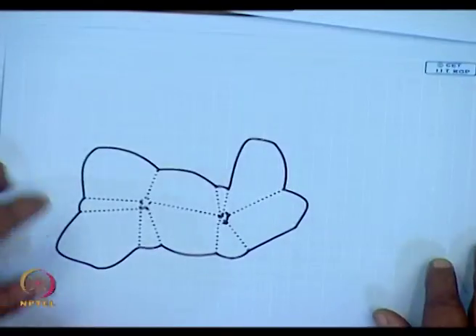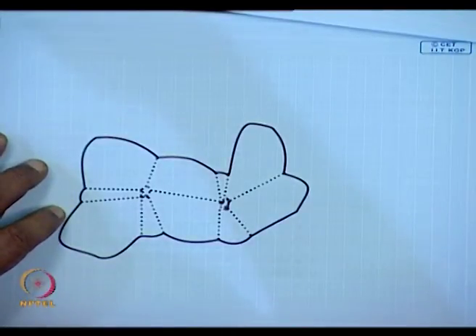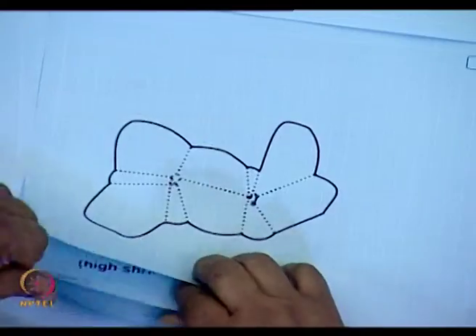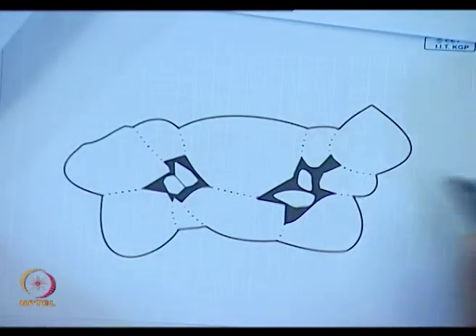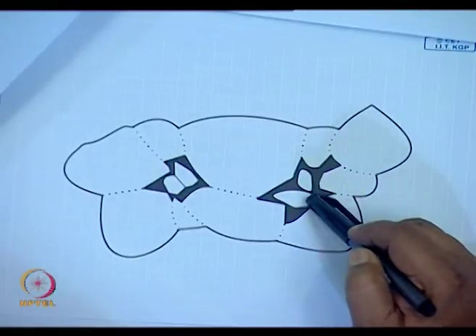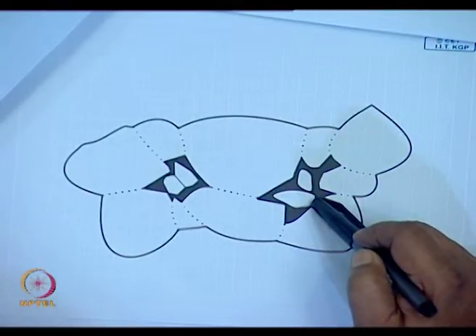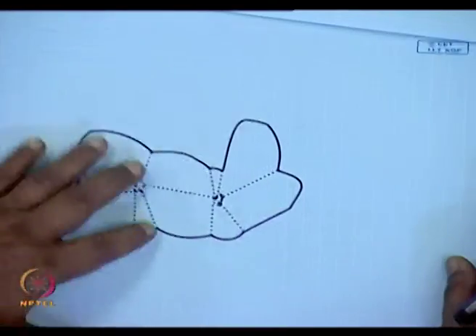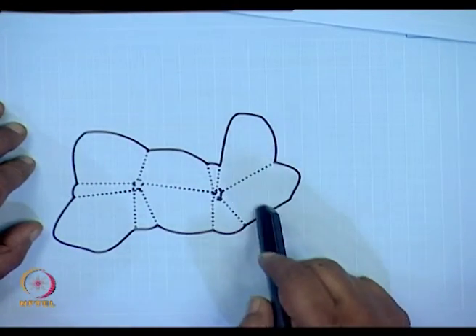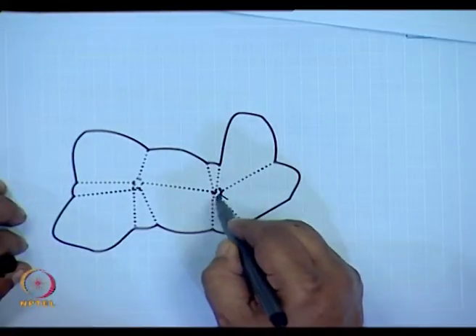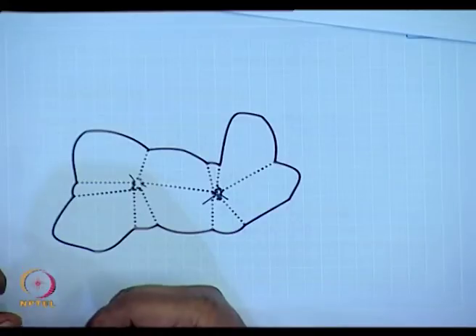In the final phase of sintering, what do we expect? We expect the grains to grow much larger. And because the grains are growing larger, in this diagram, as the grains grow much larger, the pore phases will again become discontinuous. This is what you see over here - the grains have grown significantly larger and the pore phases have become discontinuous.